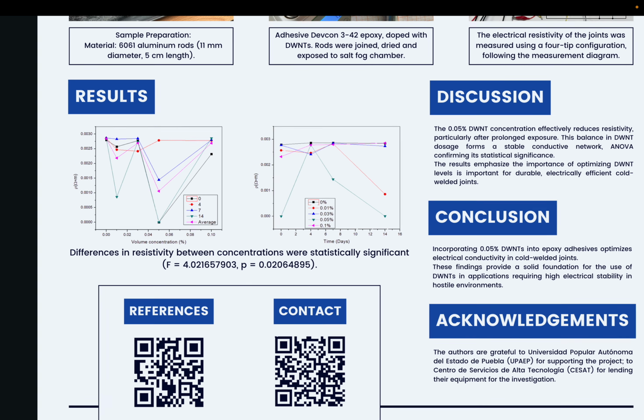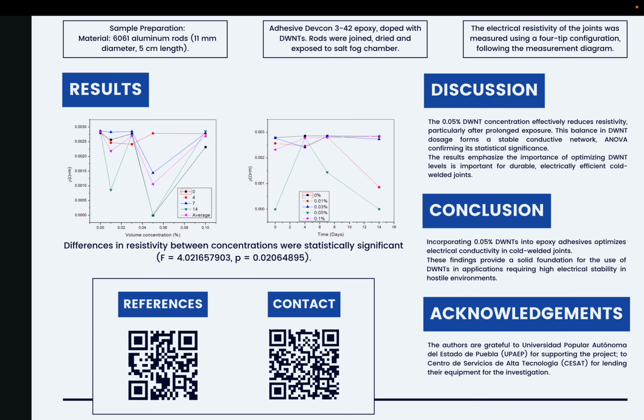In conclusion, this research demonstrates that the incorporation of 0.05% DWNTs into epoxy adhesives significantly optimizes the electrical conductivity of cold weld aluminum joints. These improvements are maintained even under challenging environmental conditions, such as prolonged exposure to the salt chamber. These findings provide a strong foundation for further research aimed at optimizing composite materials for applications that require high electrical stability in adverse conditions.